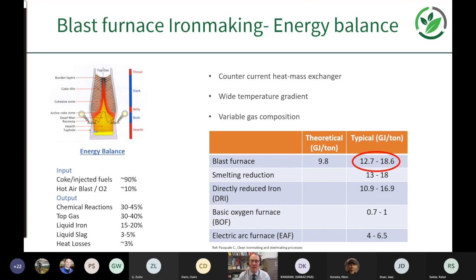So solid raw materials, coke, iron ore, fluxes are charged at the top of the furnace, and then you've got a heated blast of air that's directed in from the bottom of the furnace. So the highest temperatures are at the bottom of the furnace, which are typically raceway adiabatic flame temperatures in the region of 2200, and then at the top of the furnace you've got temperatures that are closer to 100. Most of the energy comes from this carbon-based coke or injected reductants, like injected coal, which I've been involved with. So compared to the other technologies, the specific energy, gigajoules per ton, is highest for the blast furnace.